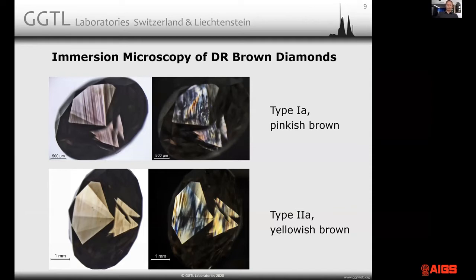You can see that both of those stones have those lamellar color zones. These color zones are often called graining. They're like brown to pink graining. The top stone somewhat pinkish, the bottom stone somewhat yellowish. And this so-called color graining is, first of all, parallel to the octahedral crystal planes. And second of all, as seen in immersion, in these lamellar planes you have a distinct light extinction on the cross-polarizing filters. This means that you locally interrupt the isotropic character of such diamonds, and they're actually anisotropic locally. This is why you have a black extinction along those colored lamellae. And that's one of the most characteristic things of such diamonds.